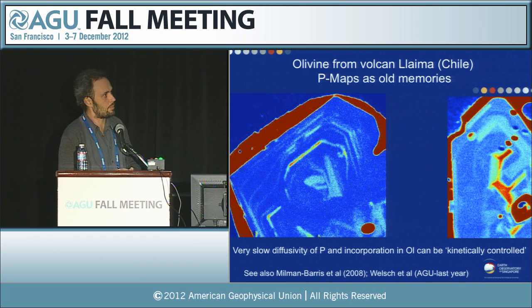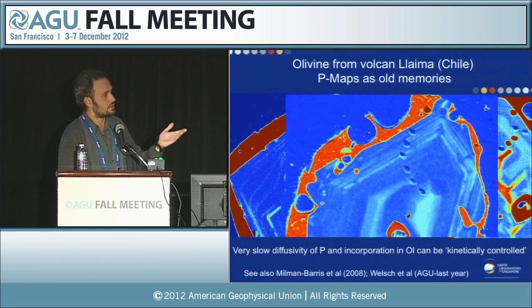Some examples of these Llaima crystals. These are phosphorus maps. You can see this is skeletal growth here, very different zoning from what we see in iron and magnesium. And this is the crystal that we will be working with most. You see these high phosphorus zones here, and you have a melt inclusion here, showing that this was probably fast growth and entrapment of inclusions, followed by a quiet period and some oscillatory zoning, and finally some dissolution also.